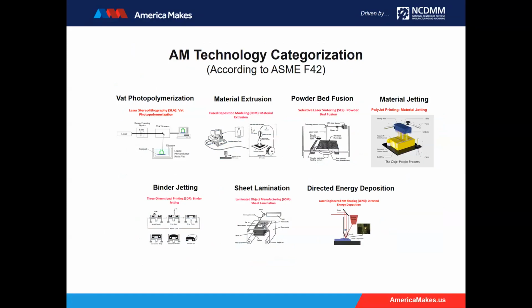filament form, is melted by the head and then put under some pressure to extrude out, just like extrusion of toothpaste, layer by layer. In the case that we are trying to extrude ceramics, that would be difficult to put into filament form unless the viscosity is very low. In that case, we could just make paste directly, which could be organic or aqueous paste.